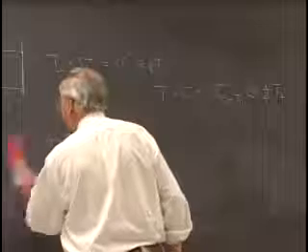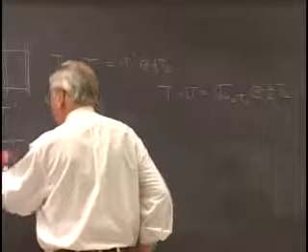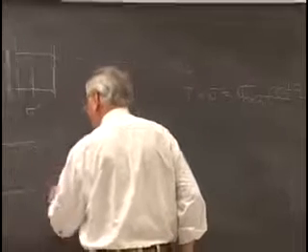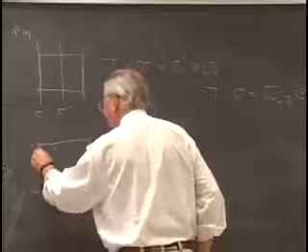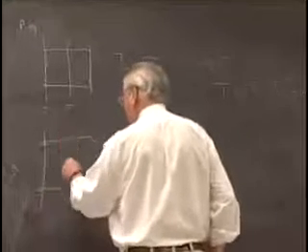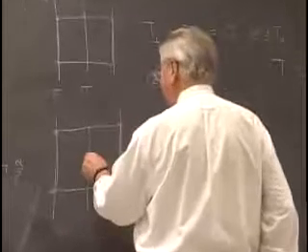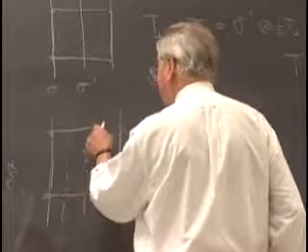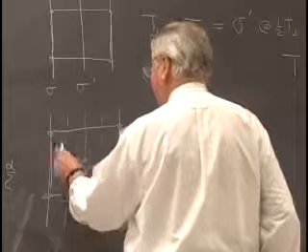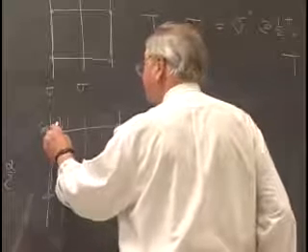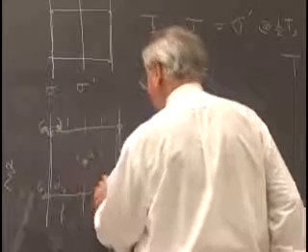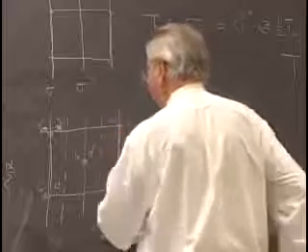So using that theorem and completing the mirror planes that hang at the lattice points, we have a very interesting group that consists of a centered lattice, mirror plane hung at the corner lattice point. This is also a lattice point, so we automatically get the mirror plane in the middle of the cell. And then in between, we get this new two-step operation, the glide plane. And the pattern that's representative of this plane group is, as advertised, just what a mirror plane does. And that is hung at every lattice point of the centered rectangular net.